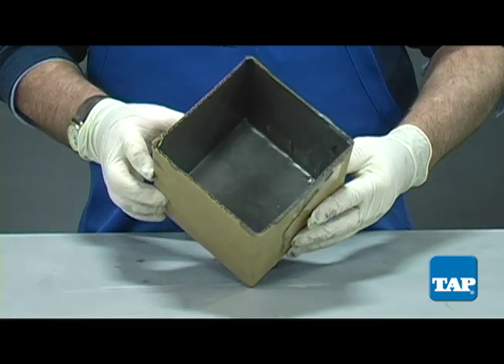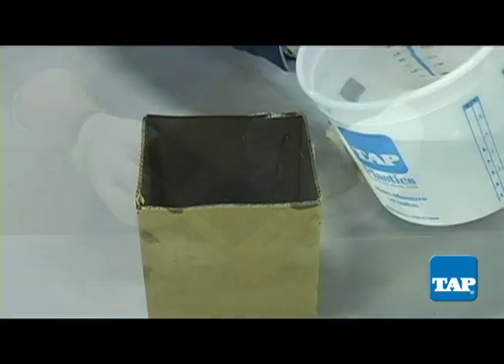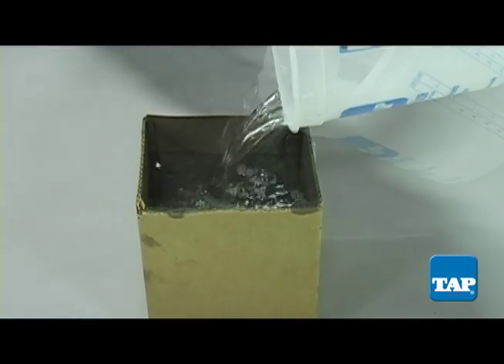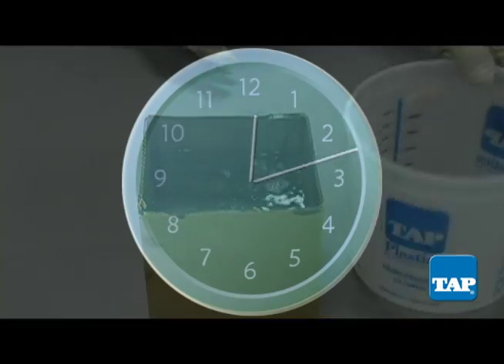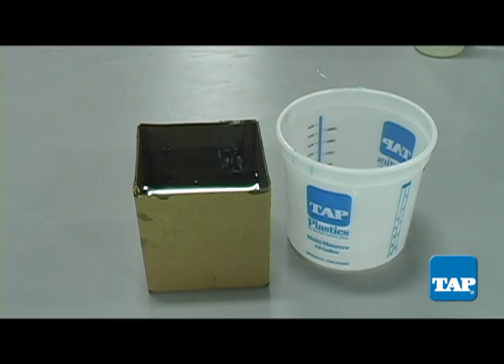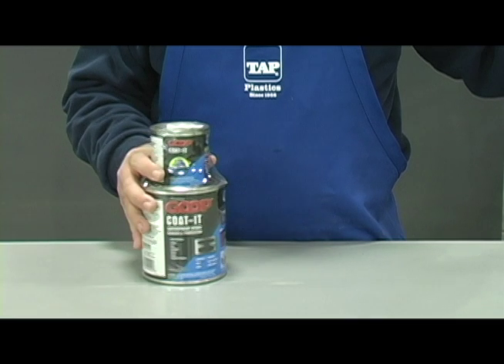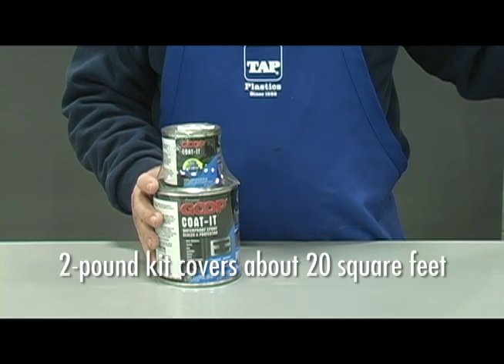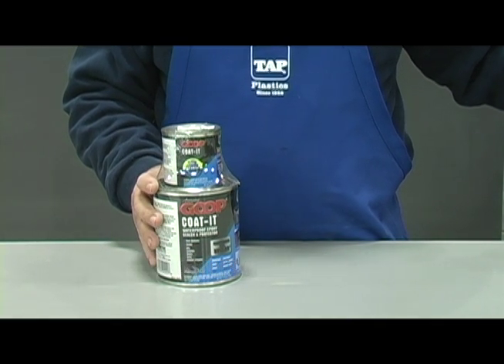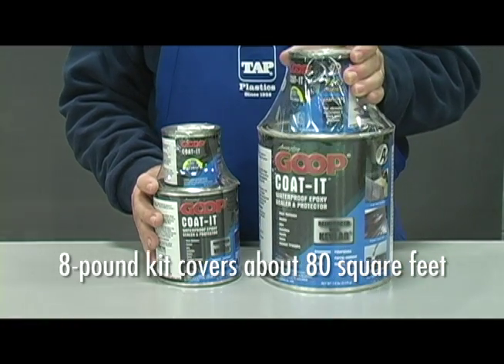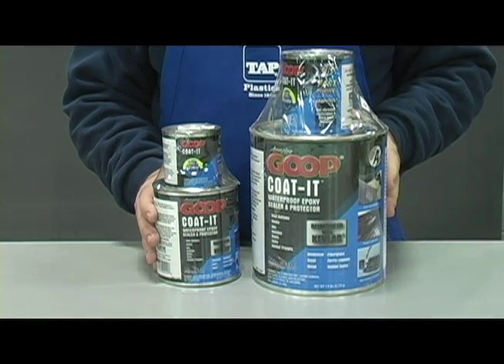To demonstrate the waterproof nature of Coat-It, we coated the inside of this cardboard box. 24 hours later, our cardboard box shows no sign of water penetration. Because of its waterproof characteristics, Coat-It can be used above or below the waterline. Coat-It comes in a 2-pound kit, which will cover about 20 square feet, and in an 8-pound kit, which will cover about 80 square feet.